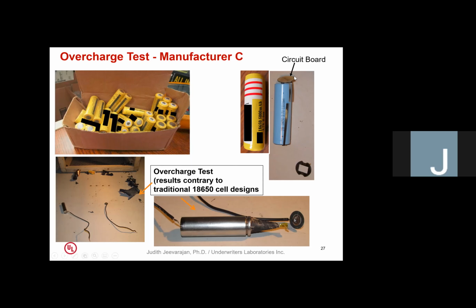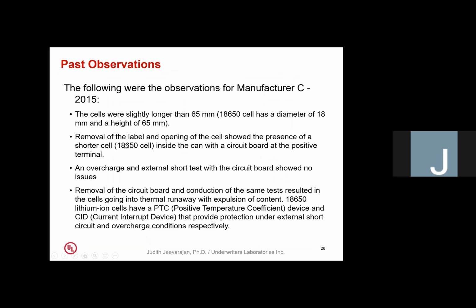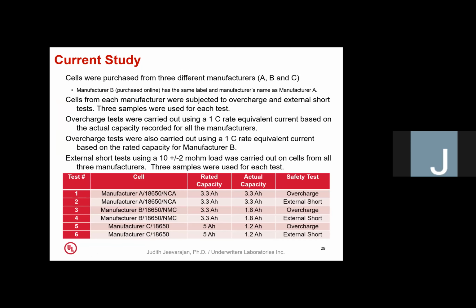So we took out the board and we tested it because 18650 cells are supposed to have current interrupt devices. And so under an overcharge condition, they should be safe. But what we found is that it expelled its contents, as you can see from the picture here. So, just summarizing what I just said, we realized that this was not an original cell, but a counterfeit cell.